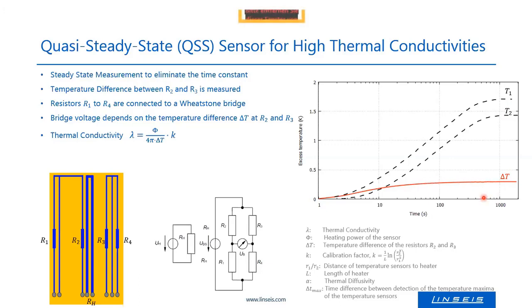And from this delta T, with the knowledge of the heating power or the heating energy, lambda can be calculated like in any other steady state method. So lambda is directly proportional to the heat energy divided by delta T. And the rest is a constant factor. This method is very suitable for good conductors. Practically, the whole range of materials can be measured. It goes up to copper and even further.